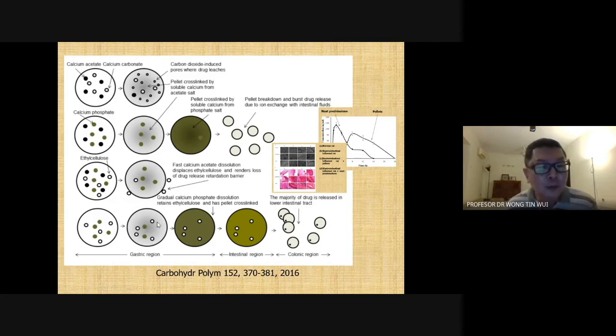Now note that the ethyl cellulose is hydrophobic. It can then prevent early drug release in the gastric regions or even in the earlier intestinal region. Now for the calcium phosphate, it is a moderately water-soluble calcium salt. So upon transit from gastric to intestinal regions, this calcium phosphate will gradually dissolve and release calcium to cross-link the alginate matrix into a denser microstructure. So with this denser alginate microstructure, first, it can capture the ethyl cellulose in the pellets, hence preventing the loss of ethyl cellulose. Second, it can also prevent further drug release to the external medium. So it is only when the pellets transit from gastric into intestine, followed by colonic regions, that the entire structure will break down with time and release the drugs in the colon.